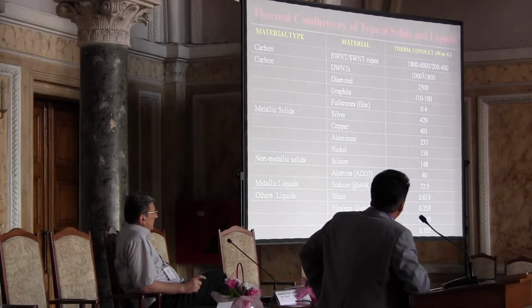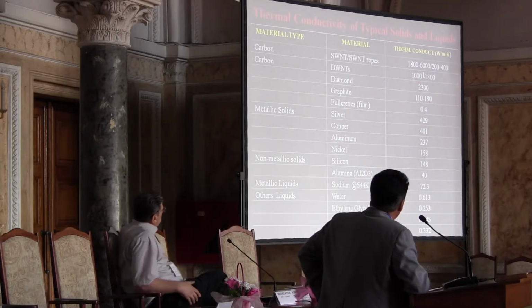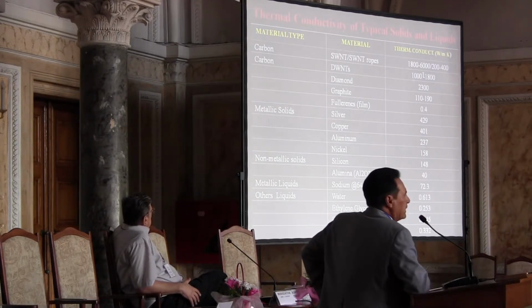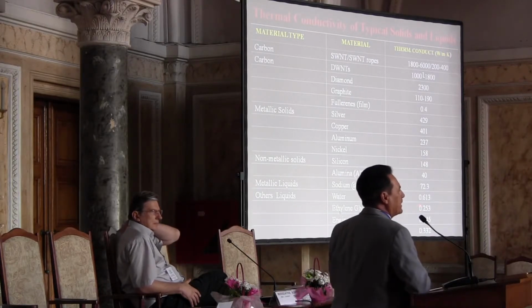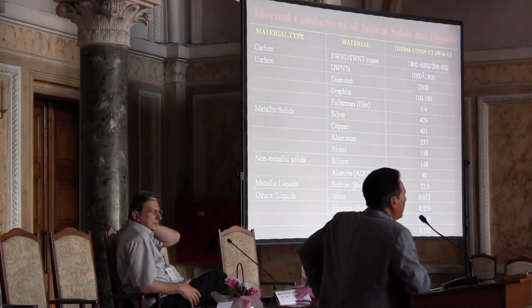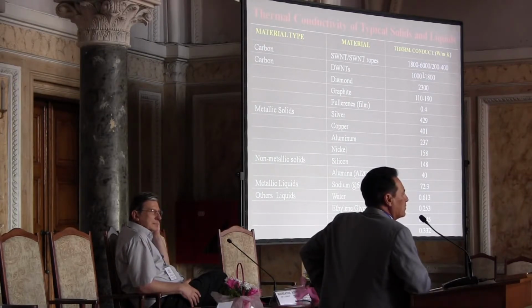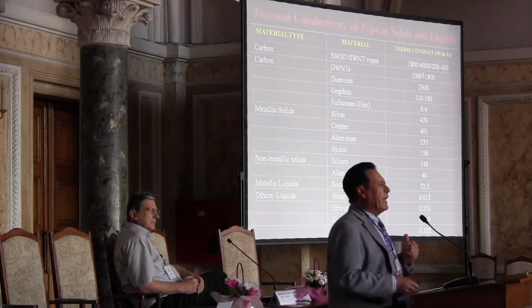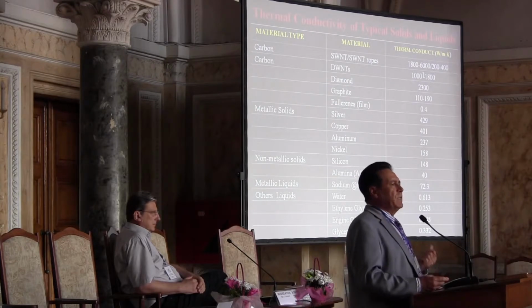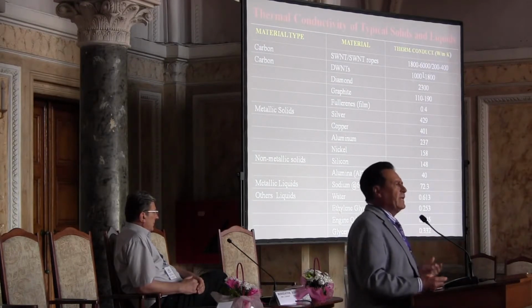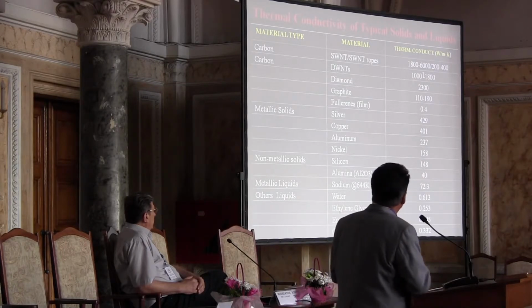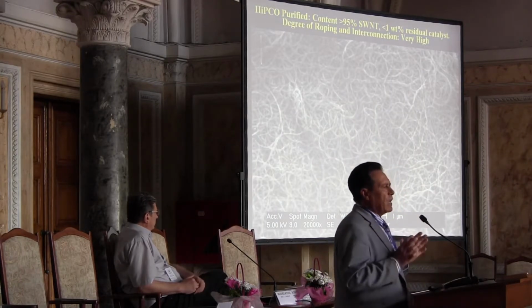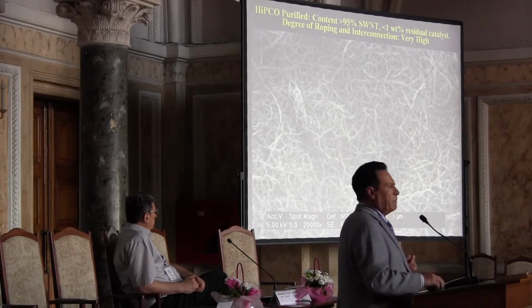The case of the double walls gives intermediate results. If you look at other matrices like water, ethylene glycol, and engine oil, the thermal conductivities are very low. So if we can control the three-dimensional nano architecture, then we can increase the thermal conductivities of these materials tremendously. In addition, we can increase the lubricities of these materials and obtain very interesting results. Let me give you a typical example of the challenges, and with graphene we face similar situations.